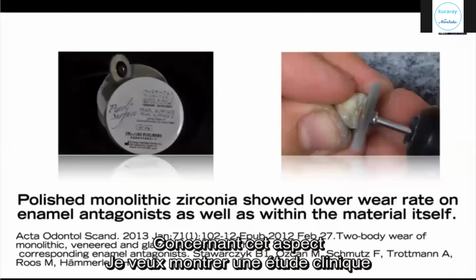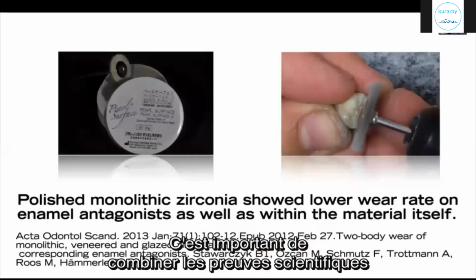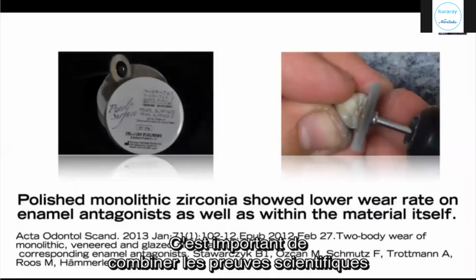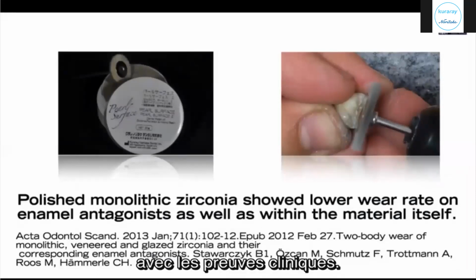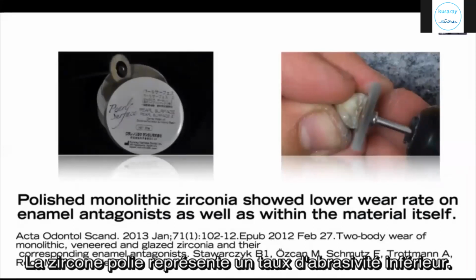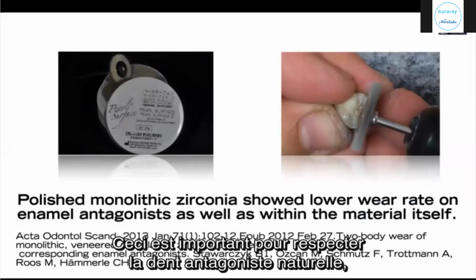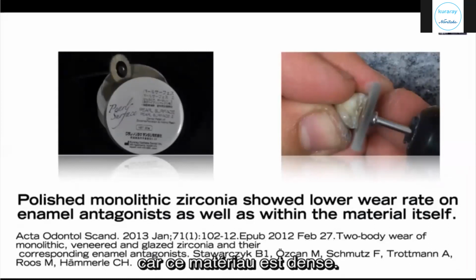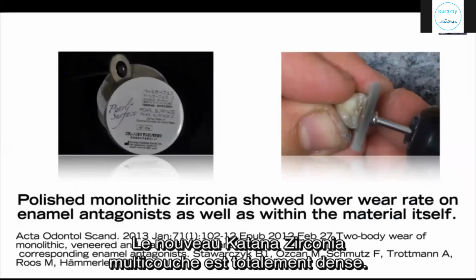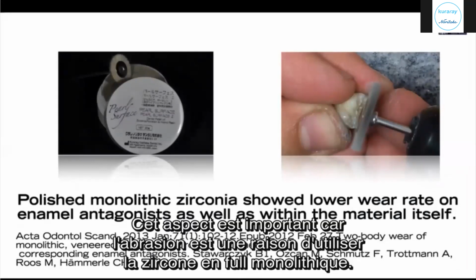Regarding this aspect, I want to mention one clinical evidence, one scientific evidence. It is always important for me to combine the scientific evidence with the clinical evidence. And from my experience, the polished monolithic zirconia represents a lower wear rate. This aspect is very interesting to respect our natural antagonists. The new zirconia Katana multi-layer is totally compact, and it's another reason to use the mono full contour solution.